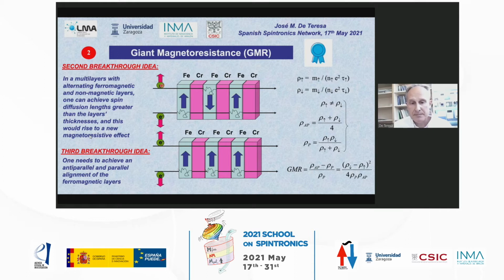In the spin-up channel, what you will see is that only in the ferromagnetic layers with antiparallel magnetization will it suffer scattering. It's the same for the spin down electrons. In this case, only the layers with magnetization in the other direction will suffer scattering. Okay, so you can calculate the total value of resistivity, and it is this value.